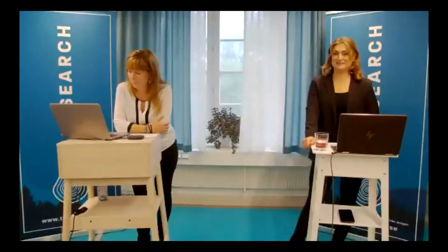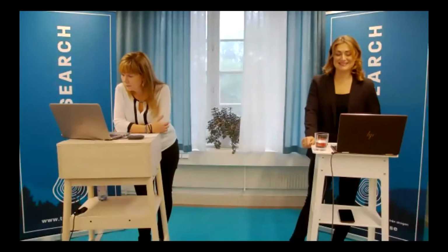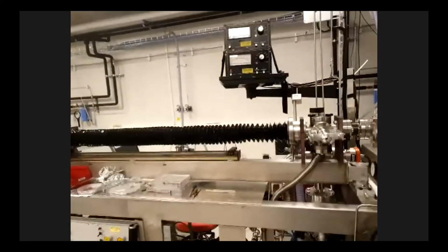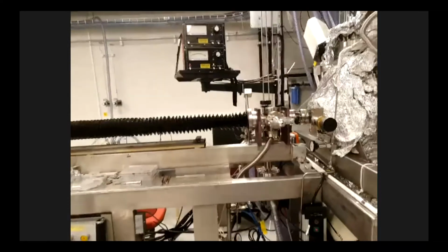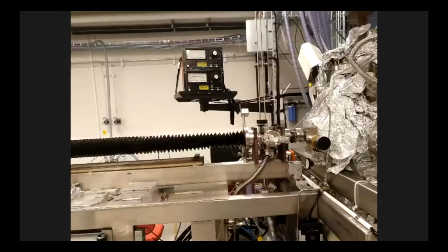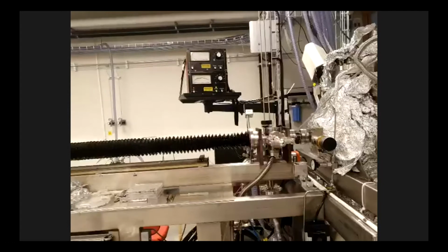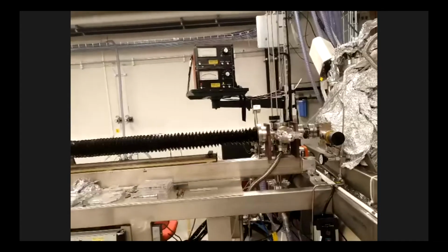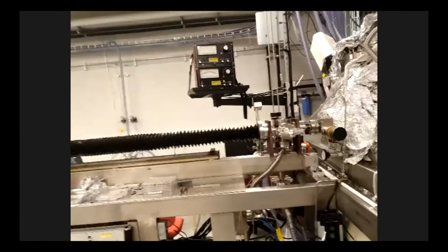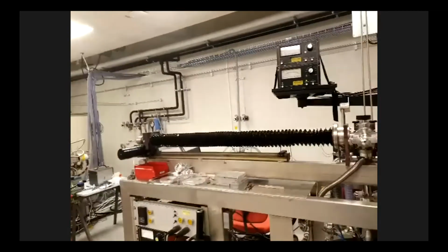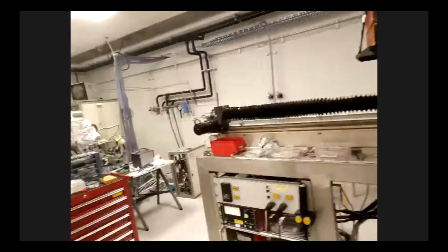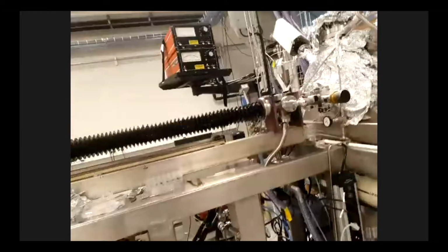How thin? It depends on how insulating they are. We have looked at Teflon, for instance, which is a very good insulator, but then the thickness of the films was less than 100 angstrom, so less than 10 nanometers. Wow. Okay. So it depends. If it's a conducting film, it can be very thick, but for insulating films, they need to be very thin.